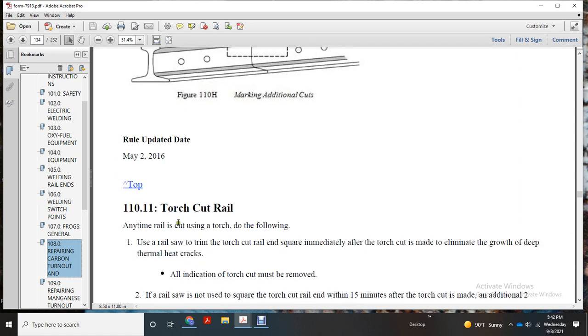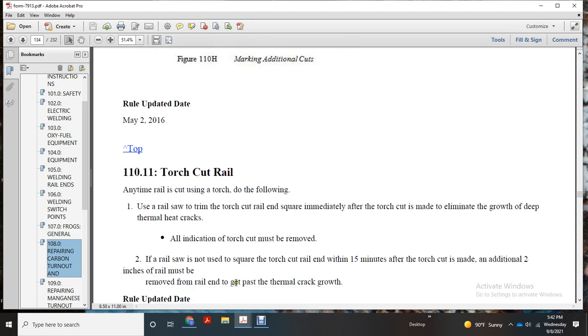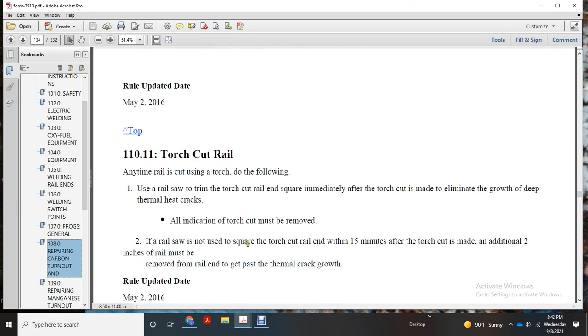Torch cut rail. Any time the rail is cut with a torch, do the following. Use the rail saw to trim the torch cut rail end square immediately after the torch cut is made, to eliminate the growth of deep thermal heat cracks. Any indication of the torch cut must be removed. If the rail saw is not used to square the torch cut, trim the rail end within 15 minutes after the torch cut is made. An additional 2 inches of the rail must be removed from the rail end to get past the thermal crack growth.